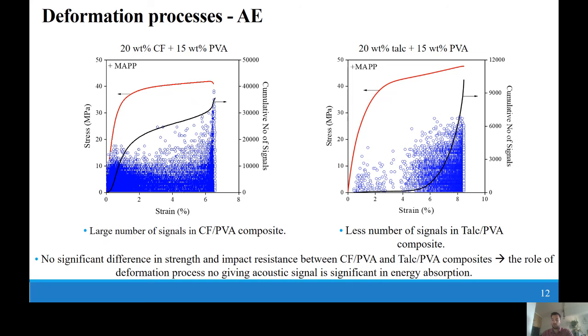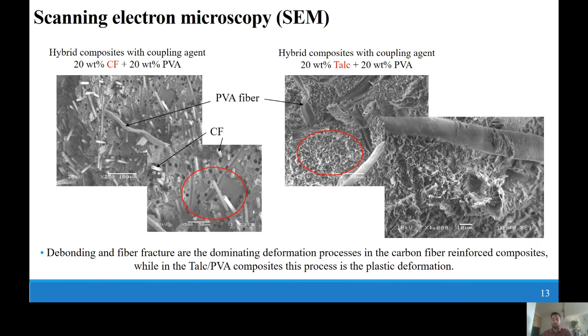As we have seen before, no significant difference was observed in the strength and impact resistance of carbon fiber PVA and talc PVA hybrid composites, but the mechanisms of the failure are different, as we can see here and on the next slide. This observation is also proved by the presence or even absence of acoustic emission signals. However, these different processes absorb almost the same amount of energy.